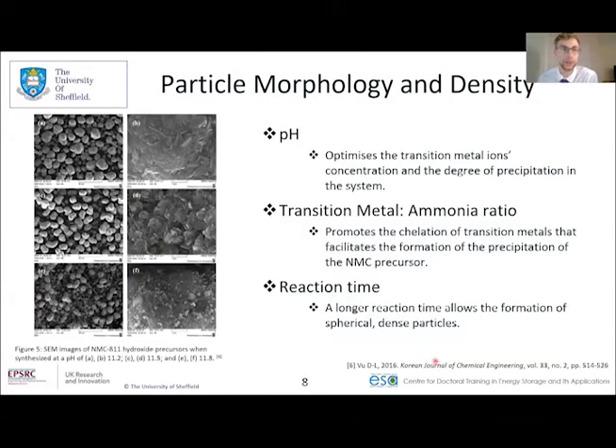Within the reactor vessel for the precursor, there are three main factors that sort of affect the particle morphology and the density, which affects the overall performance of the cathode material when it comes to its life as a cell or as a battery. There's the pH, the transition metal to ammonia ratio, and the reaction time. Now, the pH affects the precipitation rate of the material. If it's too high, then the particles can precipitate too quickly and form smaller irregular particles. And if it's too low, then there's excess ions that can be